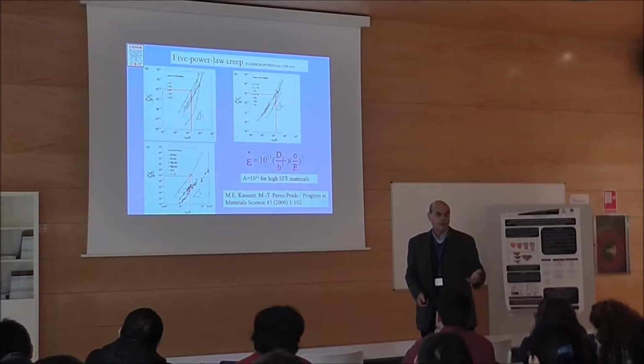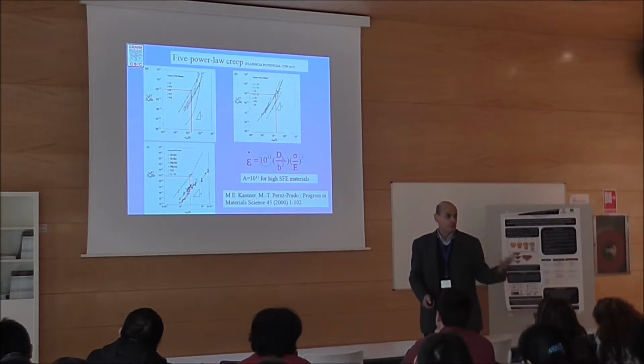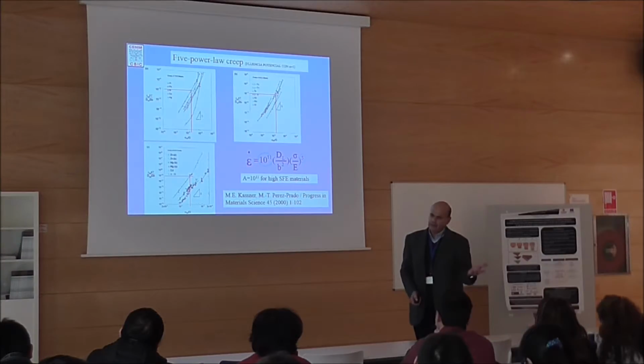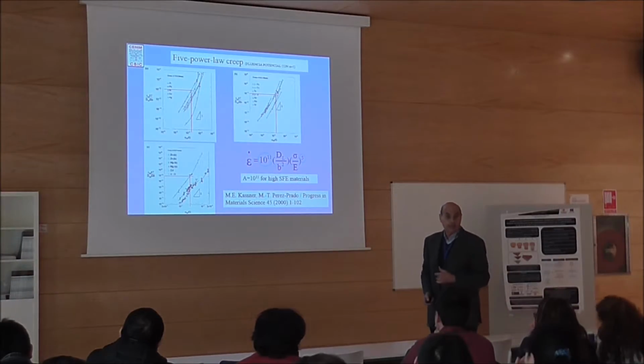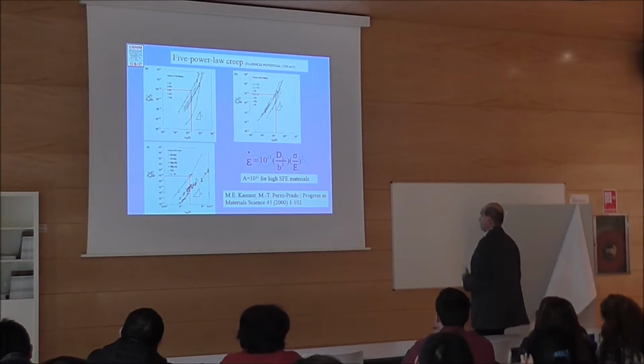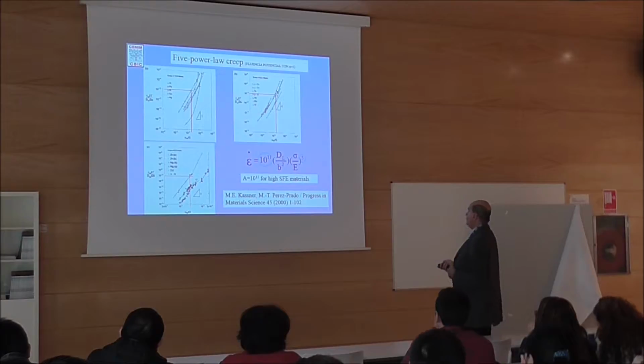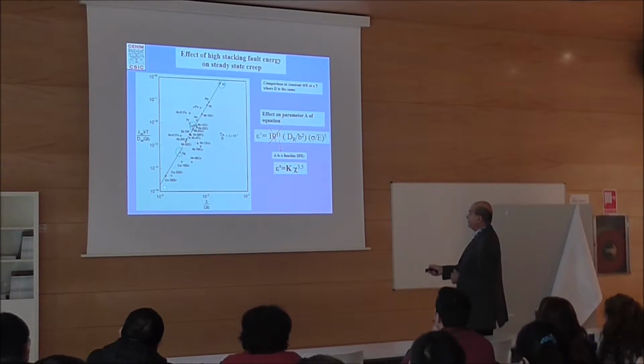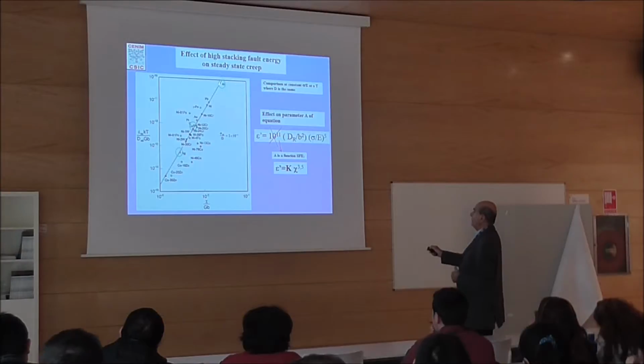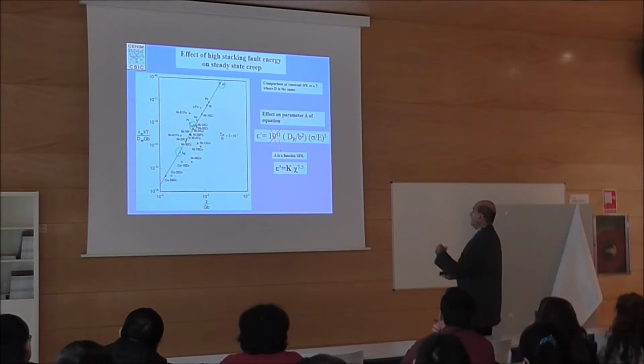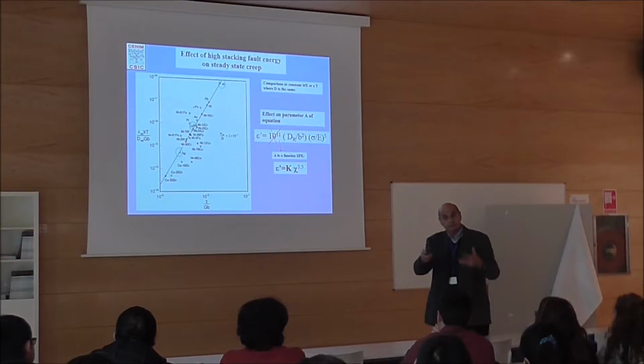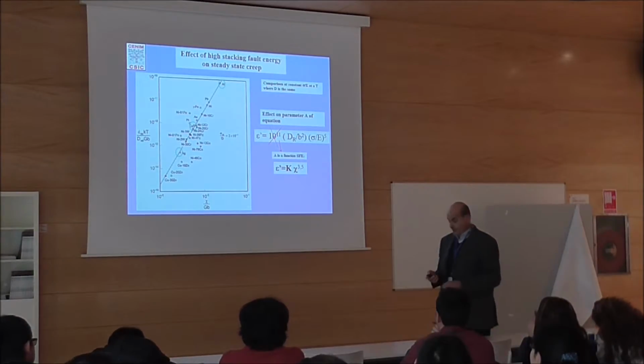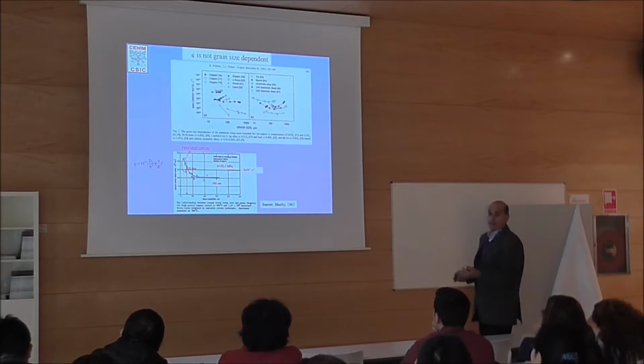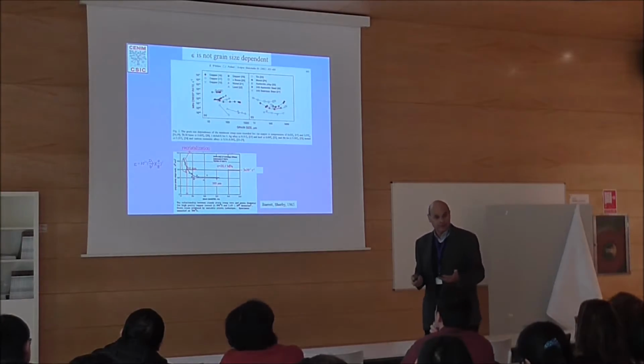I remind you, most FCC are high stacking fault energy materials, and all BCC, of course, are high stacking fault energy materials, and also many HCP, hexagonal close-packed systems, are also high stacking fault energy. If you go into the details, this is the stacking fault energy proportion. You see aluminum is high, copper and bronze and silver are low, but most of these materials will correlate to this 10 to the 11 and 5 here. And in the paper from Taleff, you can also use the same equation. This is just to demonstrate that we have no grain size dependence on the strain rate.